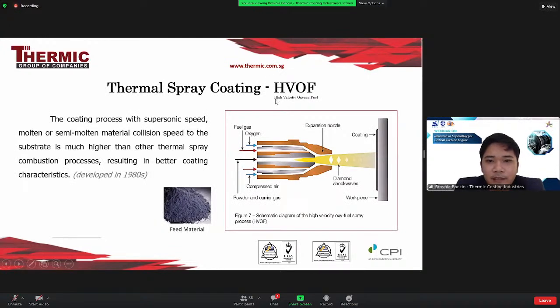This is the HVOF coating. What is HVOF? HVOF is high velocity oxygen fuel. We can see the principle of the HVOF process: oxygen and fuel gas. HVOF can use liquid fuel or gas. In our workshop we use propane in the form of gas. The spray motion of HVOF is at supersonic speed. In the motion, diamond shock waves can be formed because of the speed of spraying onto the component, the workpiece. The feed material for HVOF is very, very fine powder.